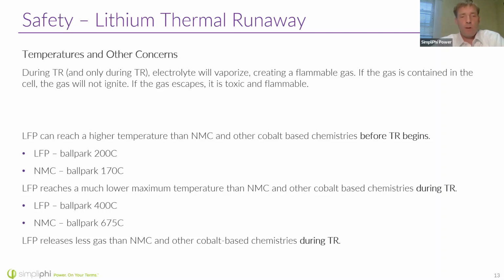Again, lithium iron phosphate, the safer battery here, doesn't get as hot. Even if we push it by putting it inside an oven to catch fire, that fire will burn at a much lower temperature, around 400 degrees Celsius, compared to 675 for nickel manganese cobalt oxide batteries. So again, this is just highlighting the safety of LFP batteries. And when you're putting batteries inside a house or an apartment building, this should be an important consideration. Really, LFP is the only battery that should be used in home battery backup.